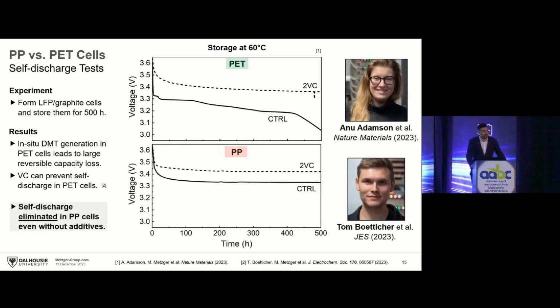But we don't even need the additive, right? If we change the tape to polypropylene, you see the voltage of the battery cell stays high over these full 3 weeks, even with the control electrolyte. So there's absolutely no self-discharge anymore in these cells if you replace the tape and change it to polypropylene.